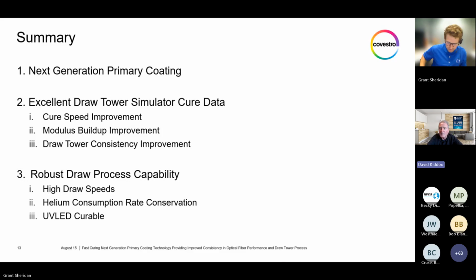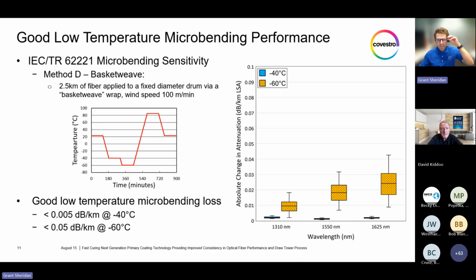How does the microbending compare to the current coating technologies that are commercially available? For our current coating technology, we have been able to further push the low temperature microbending performance, with better performing change in attenuation, especially at -60 degrees C, where we really challenge the glass transition temperatures of these primary coatings. So we've been able to further advance and further decrease the change in attenuation at the very low -60 degree limit.